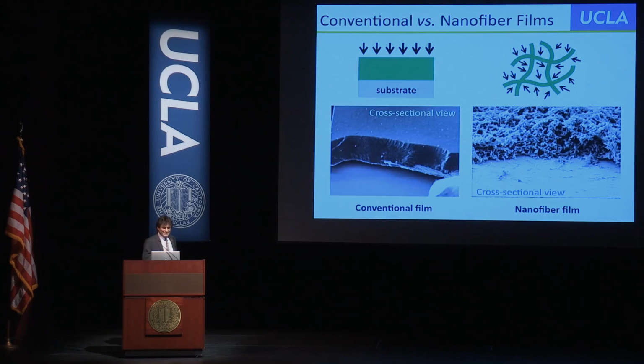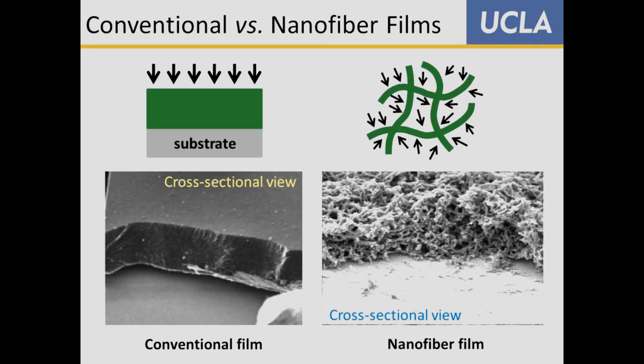And so we thought we had a really interesting sensor type material. The reason it does this can be seen if you look, here's a conventional material. When the acid comes in, of course, it dopes the surface, but in order for the conductivity to get through, you have to diffuse the dopant and it's got to send the signal. On the other hand, here's our nanomaterial on an electrode surface. Of course, in this case, there's no diffusion barrier, so the gas can come in, and as soon as it hits one of these surfaces, it sends an electrical signal, and we get a very instantaneous response.